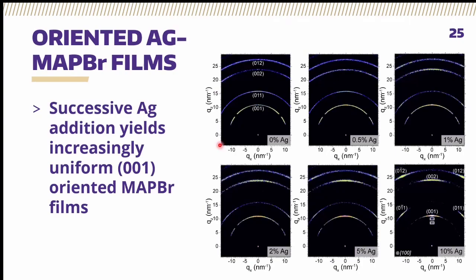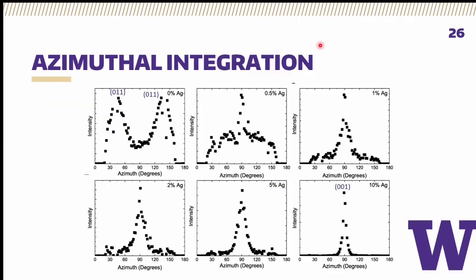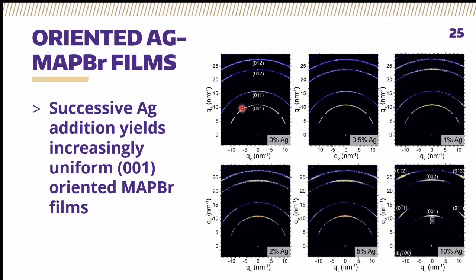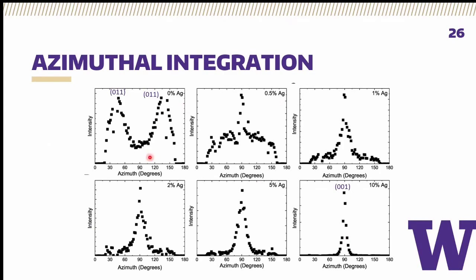And we showed that adding monovalent silver to our precursor solution induced very strong uniform 001 ordering in our thin films, from these apparently randomly oriented grains in the silver-free cases of spin coating deposition. And these are on silicon substrates. Integrating this 001 peak as a function of azimuth angle, we're able to see that, in fact, we don't have perfectly randomly oriented grains without silver. We actually have weak 011 oriented grains that soon get replaced with a very strong 001 ordering with successive amounts of silver addition into our thin films.